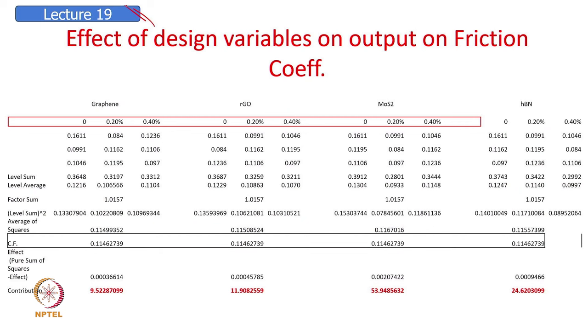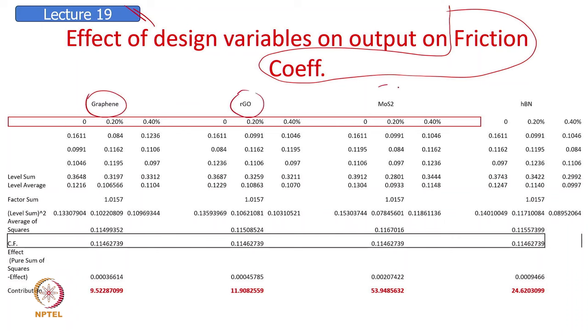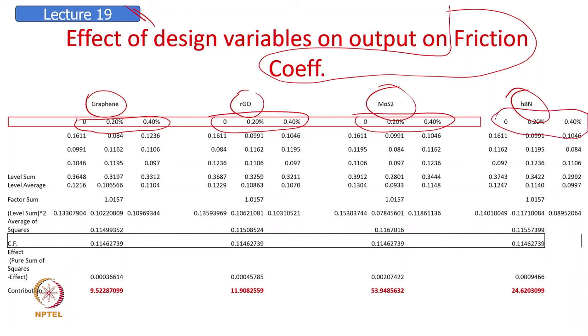In lecture 19, as we said very clearly, we use a design of experiment, because we do not have an exact relation. What we were trying to figure out was what will be the friction coefficient if we are using graphene as a nanoparticle, or RGO, MoS2, or hBN as a nanoparticle, because we don't have any equation available on this. Mathematical formulas are not there. So we did a design of experiment, giving different percentages of graphene, RGO, MoS2, and hBN, and then we performed experiments. And we tried to figure out which is the most sensitive parameter. We found MoS2 turned out to be the most important parameter, particularly for giving a low coefficient of friction. And that's why we can go hard with this kind of powder.